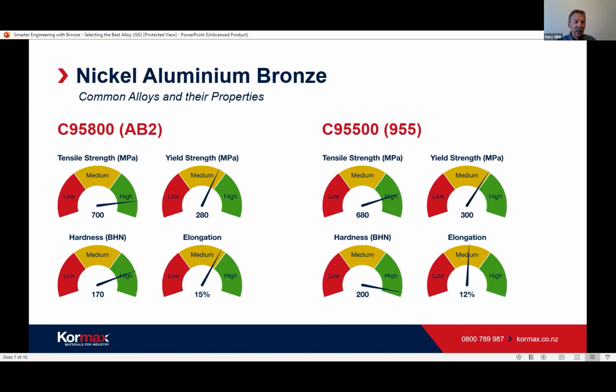So the nickel aluminium bronze, C95800 or AB2 as it's commonly known, is very good for marine use, and in fact it's approved by Lloyd's for use on ships in certain areas, but it does require an annealing heat treatment to enhance the properties. It has the same properties as the other aluminium bronzes, good wearing characteristics, but once again needs very good lubrication if it's in a bearing situation. If it's on a ship just as a fitting or something, then that's not relevant.